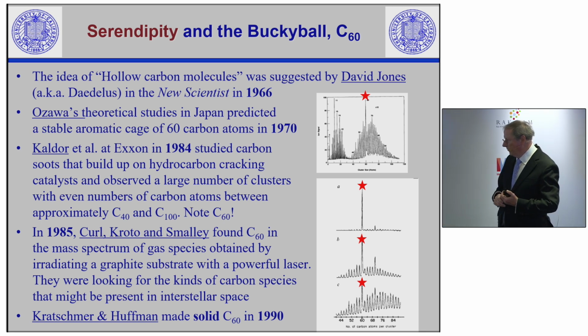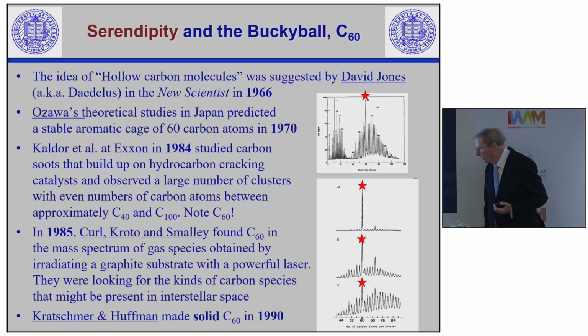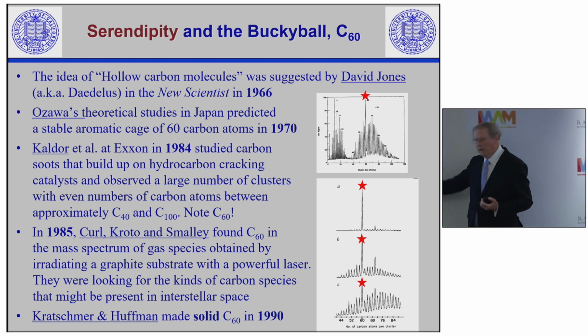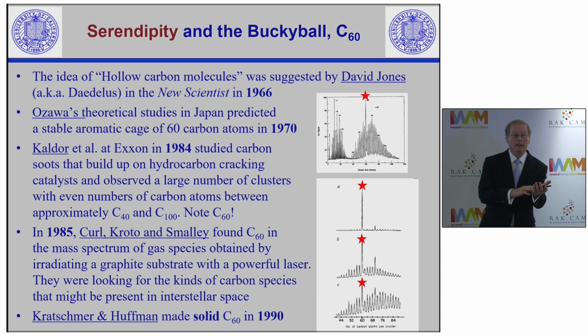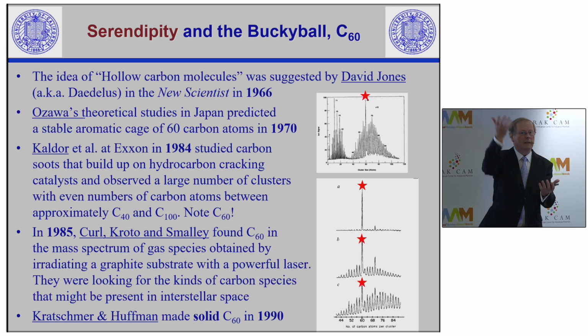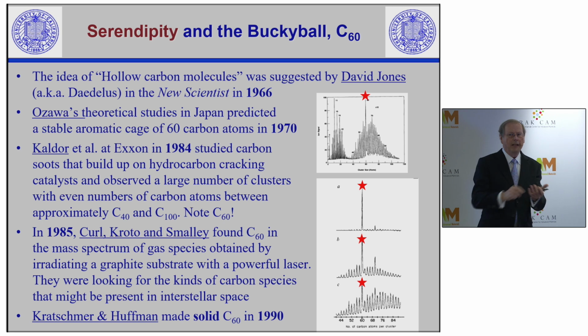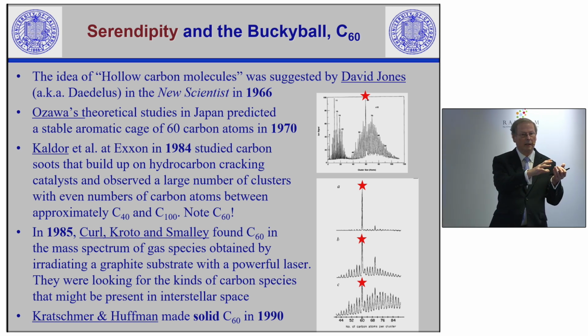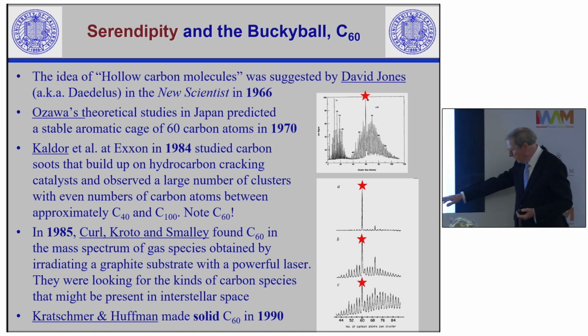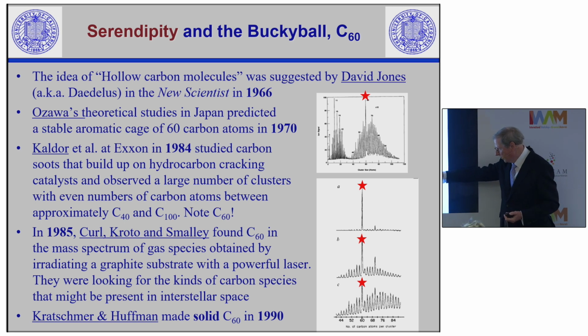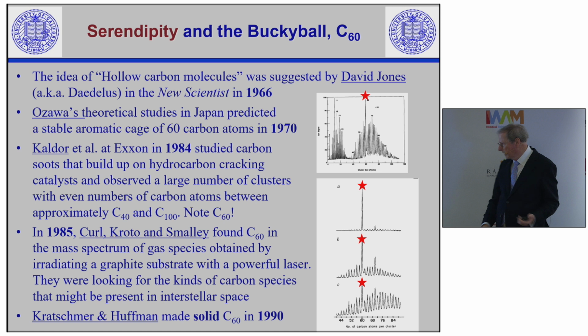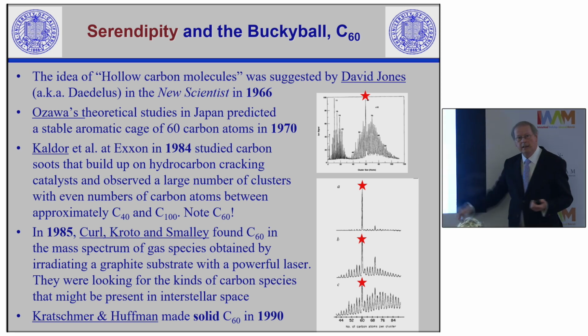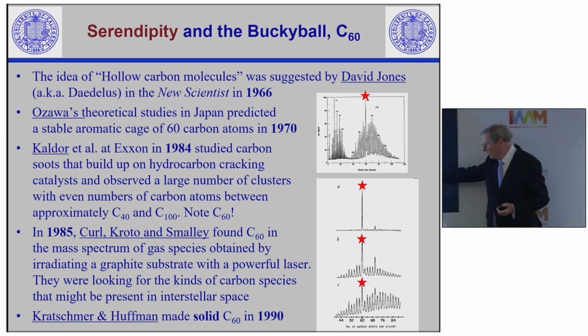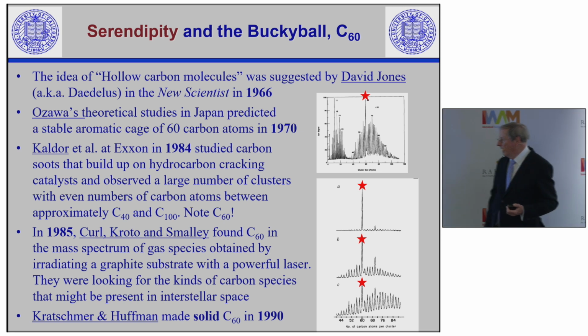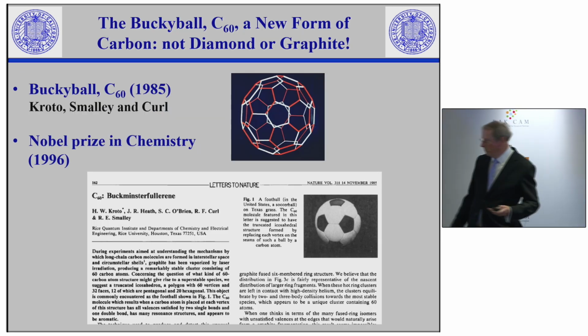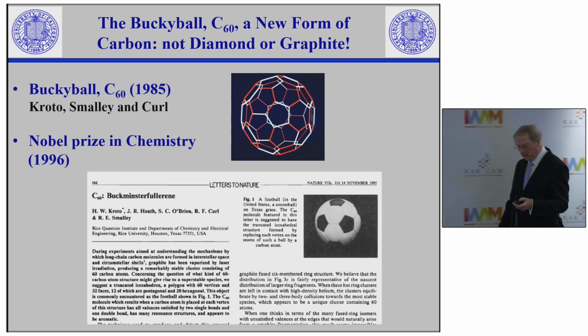A year later, at Rice University, Harry Kroto and his colleagues did the experiment a different way. They took a piece of graphite, bombarded it with a laser, and ablated carbon species into the gas phase. Depending on how they observed them and how they allowed them to equilibrate, they got different spectra. You can see C60 with the red star. If you're really careful and don't allow them to equilibrate, C60 turns out to be the dominant species, and also the C70, which was apparent here. That led to the paper I showed here, published in 1985.